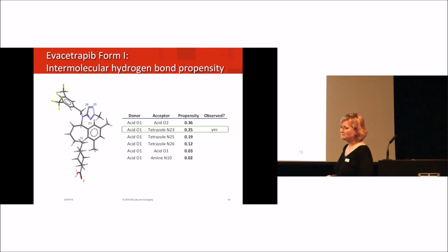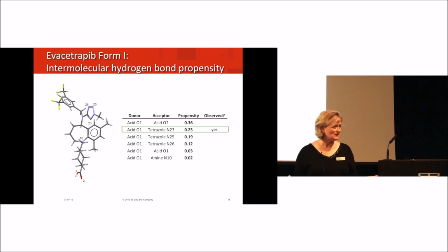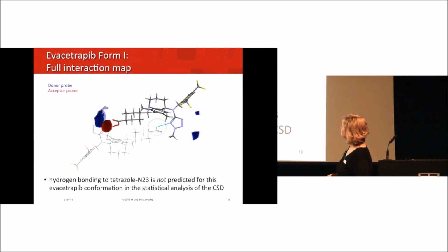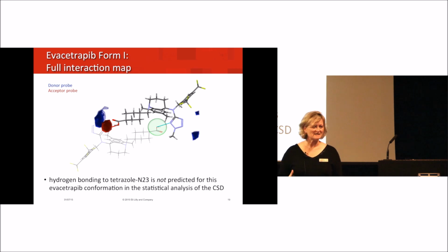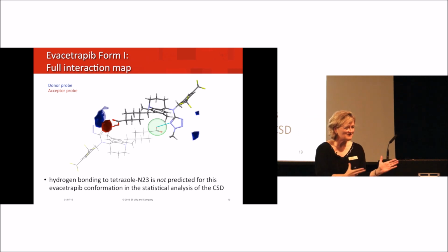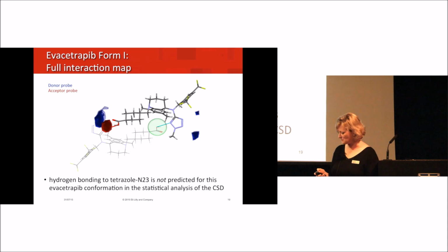But I would say that we're probably on the order of where we felt we were with the monohydrate based on this assessment. The findings ended up being interesting because we also had reasonable geometries for our interactions. But what was interesting was this N23, which was supposed to be sterically hindered, and you see there's no hot spot. This molecule was added after the fact. We thought that was sterically hindered, but in this late appearing form, it must have had to slide those molecules in just so to be able to fit that. That's not a predicted interaction. So you can ask, could that have been one of the reasons?